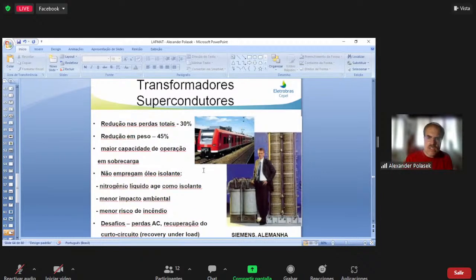Superconducting transformers are another interesting thing because you can see here a comparison between a conventional transformer and the smaller one, a superconducting transformer. Again, it's quite interesting, for example, for transportation, because you save space and it's lighter, and it has a lot of advantages. However, nowadays the progress in this area is not that big because there are a lot of problems that are not yet resolved, such as the AC losses, and you have to recover after a short circuit under load. You cannot disconnect it after the short circuit. And you have a temperature rise and have to cool down under load.